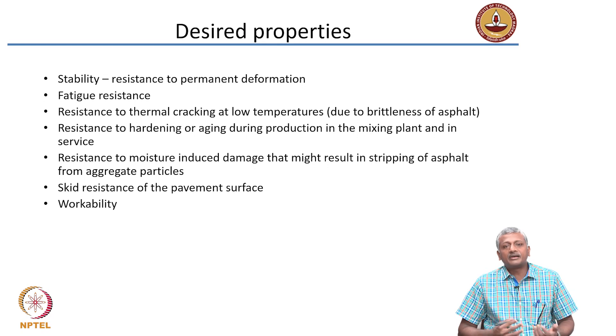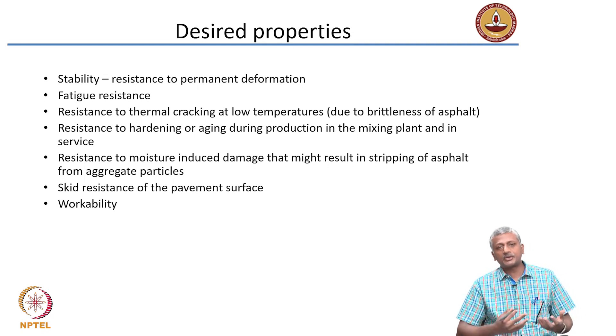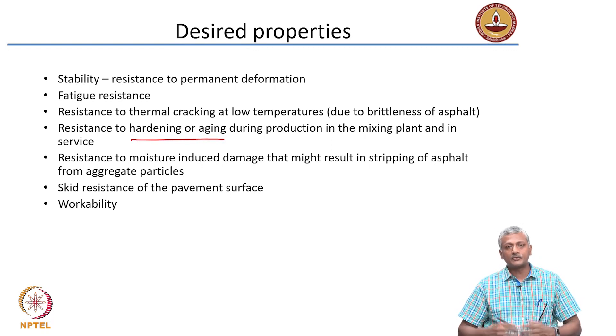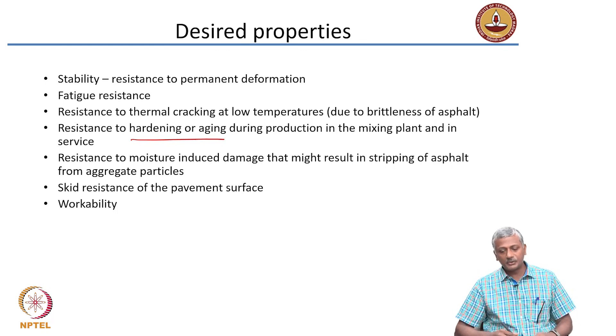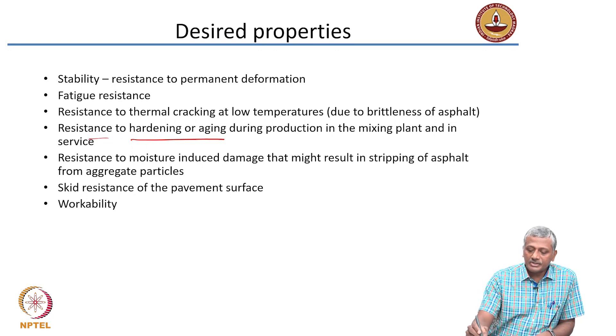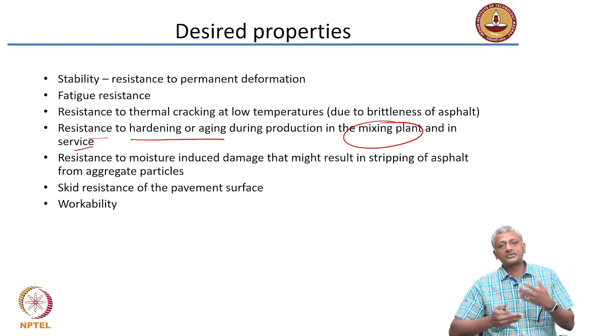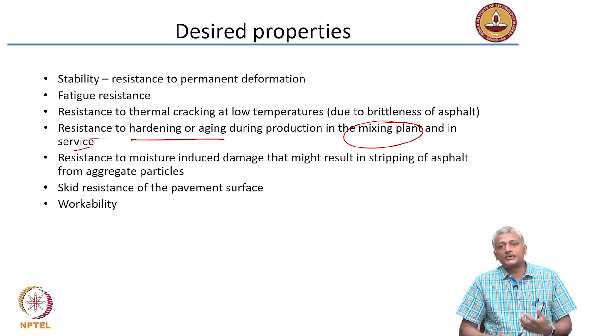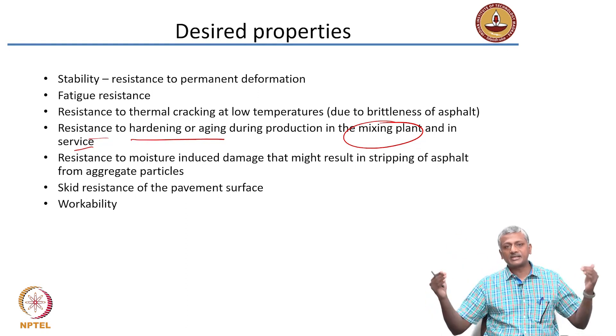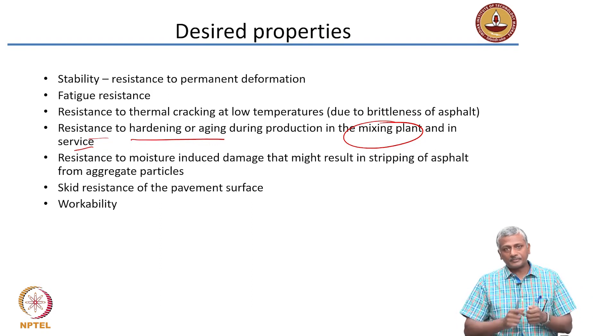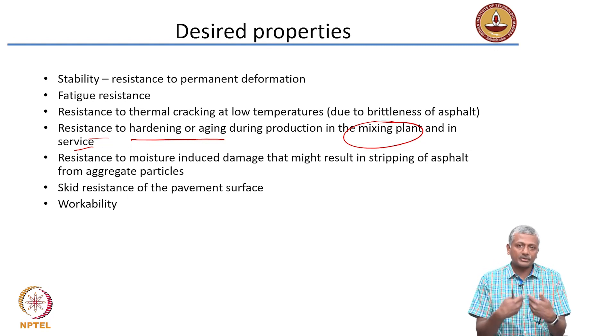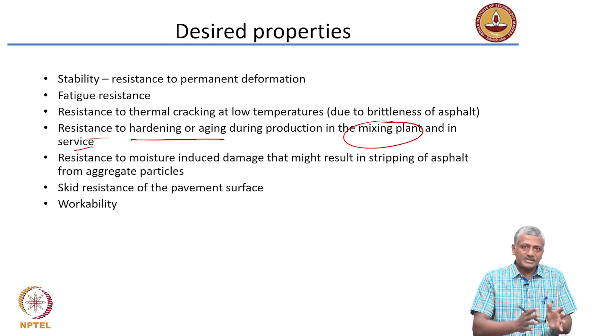Asphalt is a polymer subject to ultraviolet radiation, and the heat during the mixing process can also affect its properties, leading to a phenomenon called hardening or aging. As asphalt pavements age due to external exposure, they become less flexible and start cracking. Resistance to hardening and aging — both in service and at the mixing plant where high temperatures are used — is therefore important. Resistance to moisture-induced damage is also critical, as heavy rain can break the bond between asphalt and aggregate, causing the aggregate to strip loose.